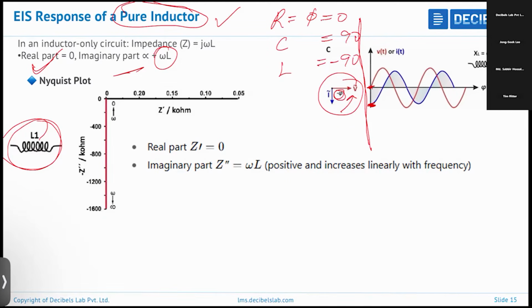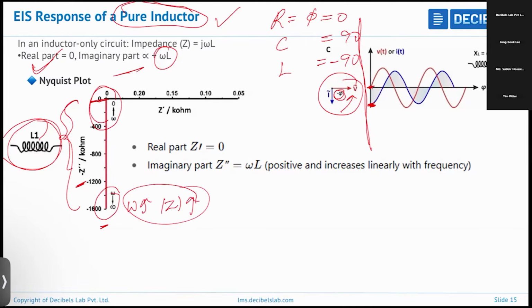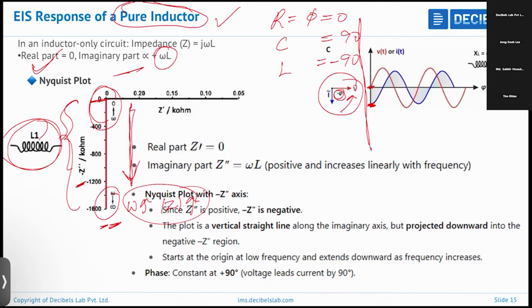And because of that, in the Nyquist plot you get the impedance value along the positive axis. Here, this portion is where the frequency is 0, and this is where the frequency is high. You can see here that when the frequency increases, Z also increases. It's directly proportional. So the impedance increases in this direction with increase in the frequency.